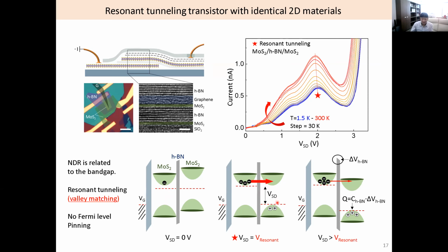And if we apply some source drain voltage, now, since there is no gap state or negligible gap state, we have some electron and hole accumulation by parallel capacitor. And then if you think about Boltzmann distribution, the Fermi level should be located very close to the valence band and very close to the conduction band. This is the resonant condition marked by the red star. So here we have maximum current. Why? We have energy matching, also momentum matching, or momenta are matched.